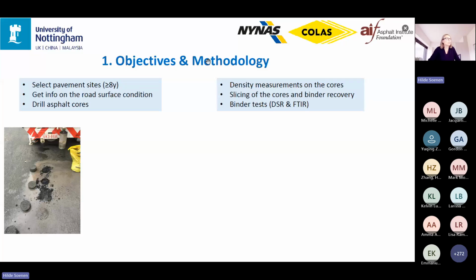Regarding the methodology, of course we first needed to select pavement sites, and we wanted pavements that have aging, so they needed to be at least 8 years old. We also wanted info on the road performance or road condition. These two conditions are not easy, so it was not about selecting pavements, but just finding pavements where we could get cores from. Once we were able to get cores, we tried to take a large number of cores from the same spot. And all the cores were taken from between the wheel paths because we were interested in the aging.